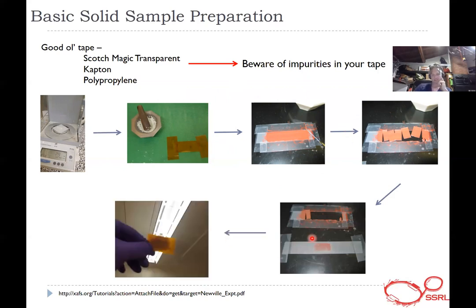And the thing you also need to do is check for pinholes. People do this to varying degrees of precision. Some people use a microscope. Or you can hold it up to the light at a bare minimum. Make sure no light gets through. This is not as important if you're doing a fluorescence experiment. You're less susceptible to problems. But if you're in a transmission geometry, you need to make sure that you don't get pinholes. It can cause a lot of problems and a lot of distortions, because then you have X-rays passing through into I1 unperturbed by your sample.